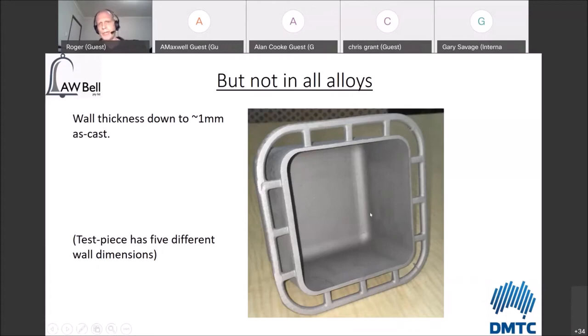So you can see the part there. You have the very thin wall over here around about 1 millimetre, and then the back wall being around about 6 millimetres. So what this did tell us was that we could cast down to these very thin wall thicknesses in this material. But one of the things that we did notice as well, and there's an example here, there's a little fin over on the side here where the shell was cracked, and there's another one over here. Basically, wherever there was a shell crack, metal filled it.